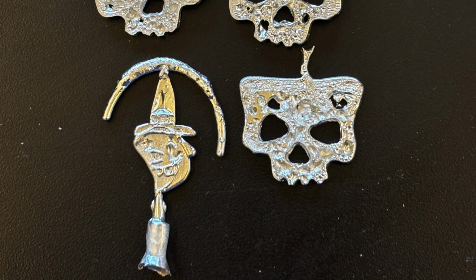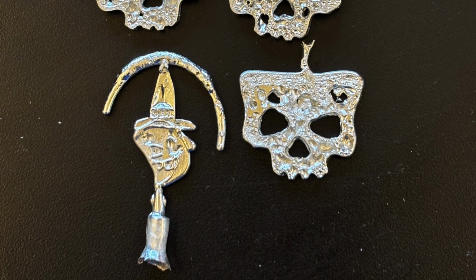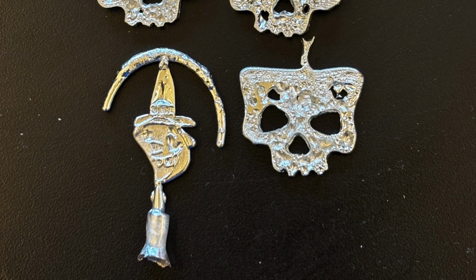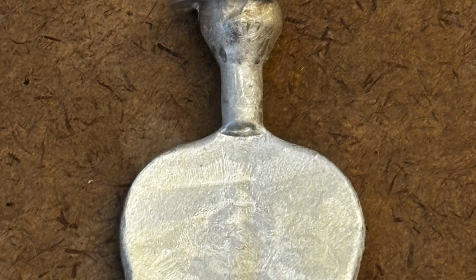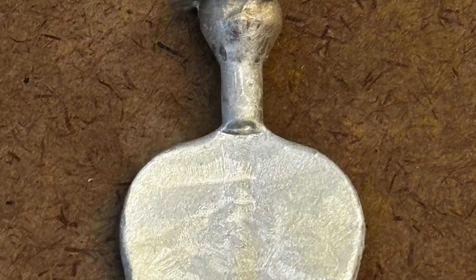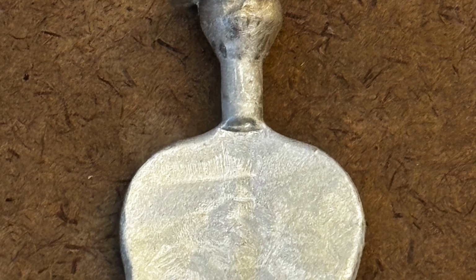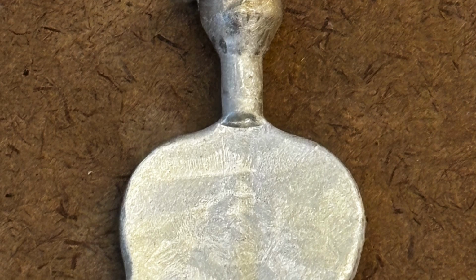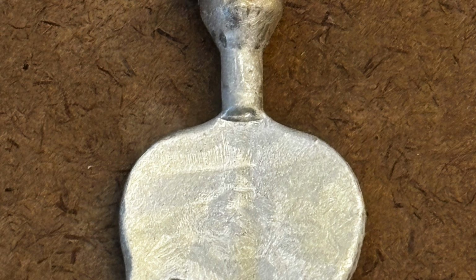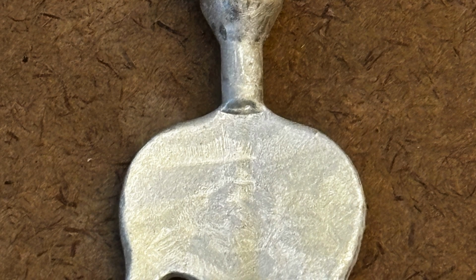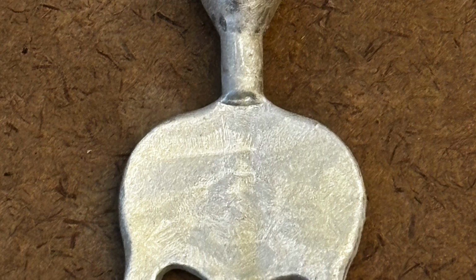So here's the castings before doing the talc, and I'm going to follow up with the casting after using the talc. So everything was done exactly the same, just a little bit of talc added into the mold there, and you can see just such a significant difference in the quality of the pewter casting into that mold.